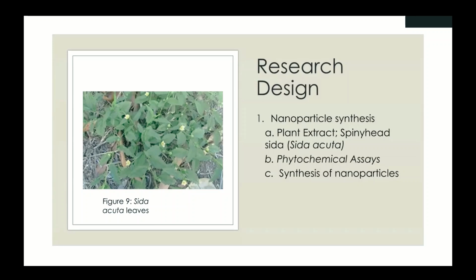Now, this is a deviation from what I just presented. As I said, we have been focusing on nanoparticle synthesis using green chemistry. These are the results of another project that a student did in which she used copper sulfate as her metallic salt, and her plant was the Sida acuta, and she made an extract using aqueous media. Then she synthesized her copper sulfate nanoparticles using the plant extract, and the plant extract had the components to allow for reducing and capping of the copper sulfate nanoparticles. She synthesized the nanoparticles at a pH of 7 for 30 minutes at 60 degrees with stirring and heating.